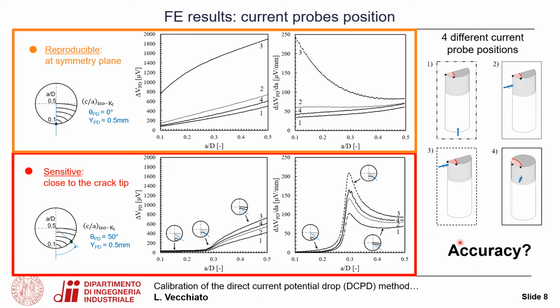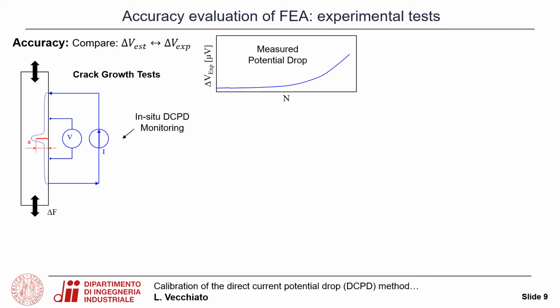The last parameter to be analyzed was the accuracy, and for doing so, a fatigue test was performed. As briefly discussed before, evaluating the accuracy of a DCPD measure means comparing the estimated value of the potential drop with the experimental one. So for doing this, crack growth tests have been performed with in-situ DCPD monitoring, so it was possible to obtain the experimental value of the potential drop as a function of the number of cycles.